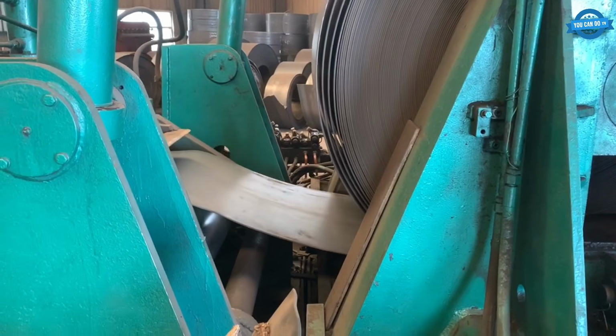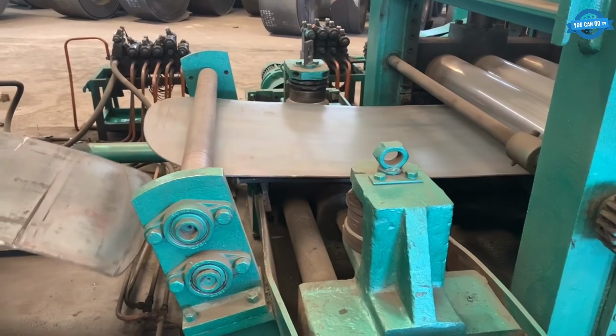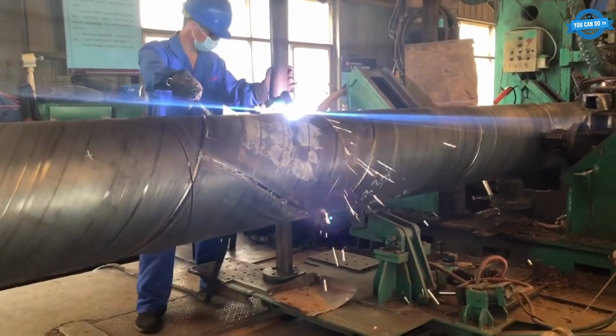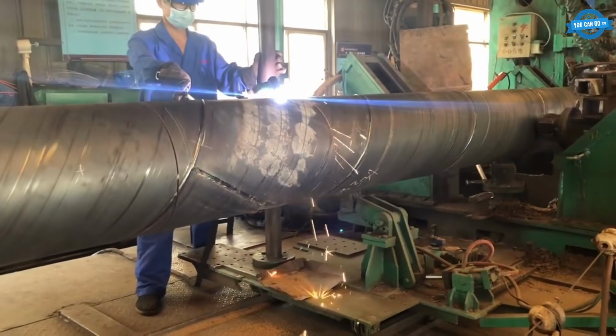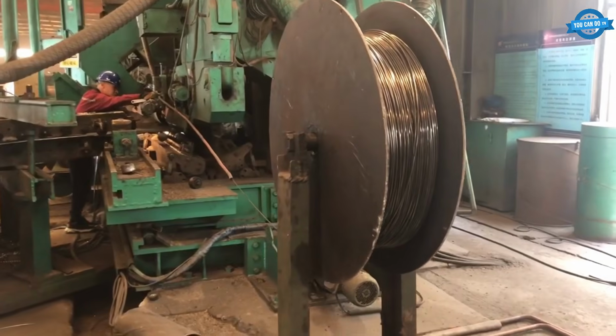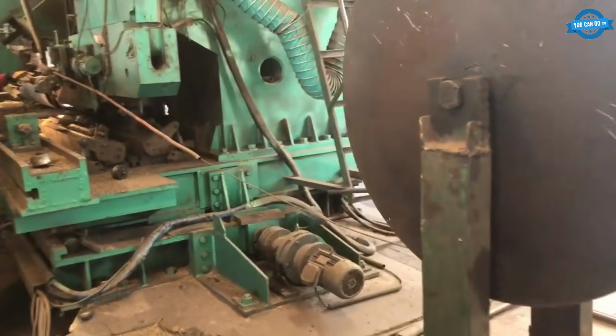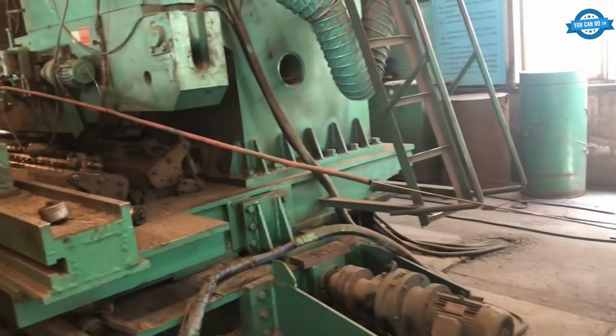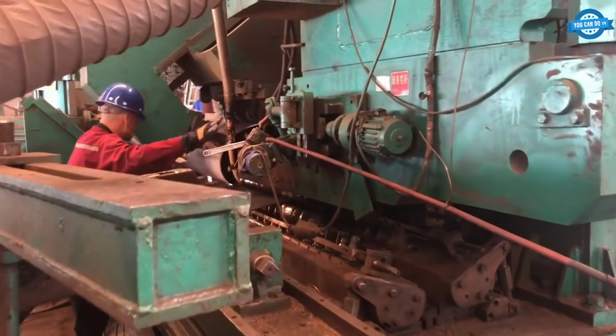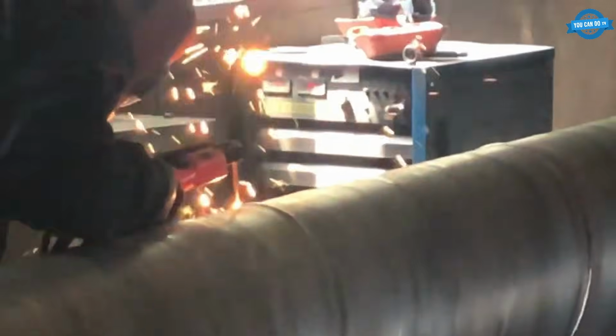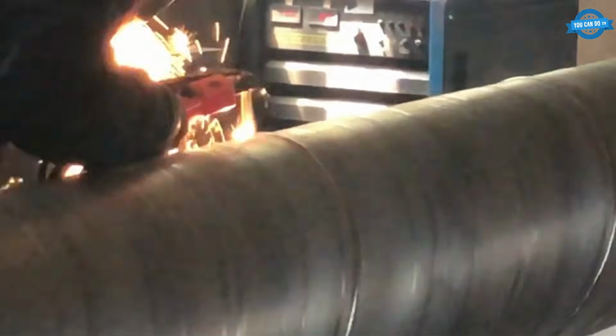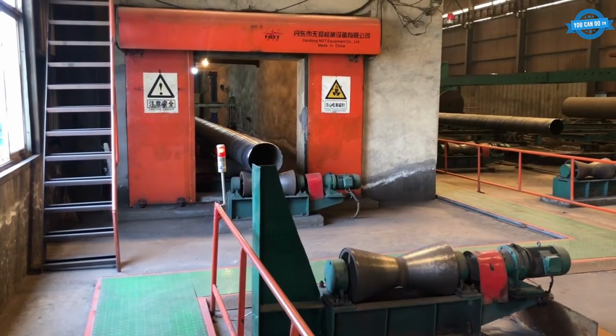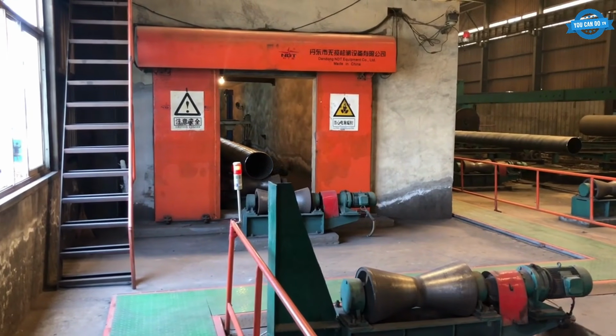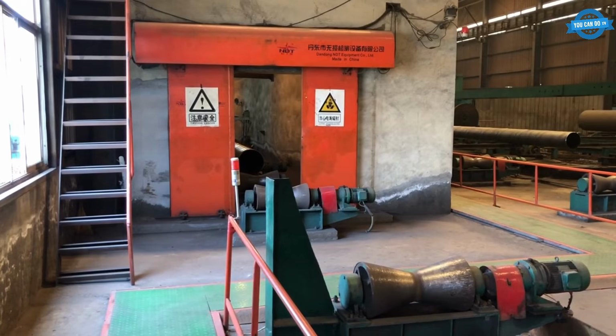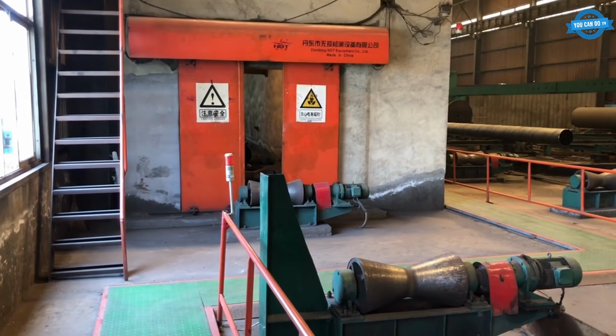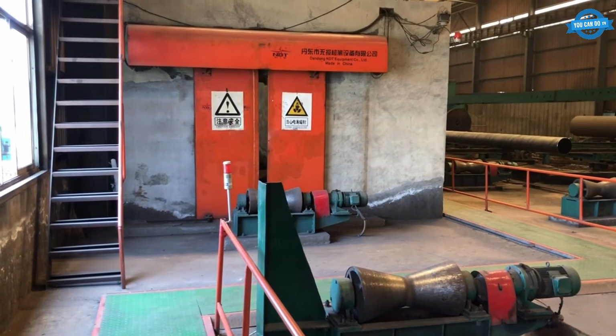Take a steel coil, feed it into a spiral-forming machine at an angle, and out comes a pipe of almost any diameter you want. Spiral-submerged, arc-welded pipe manufacturing is one of the most efficient ways to produce large-diameter pipe. A steel strip gets uncoiled and fed into the forming section at a controlled angle. The strip wraps around itself in a helix as it moves forward, with the two edges meeting along the top seam. Submerged arc welding under a blanket of granular flux fuses the seam continuously from both the inside and the outside of the pipe. Wall thickness stays uniform because the same strip is used throughout. Pipe diameter is limited only by the strip width and the feed angle. A narrower strip and a shallower angle produces a larger diameter pipe than the same strip wrapped tighter.